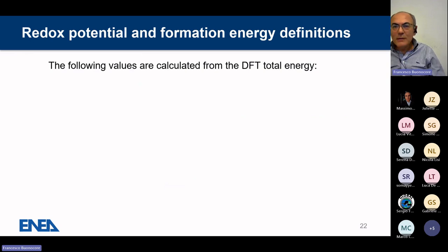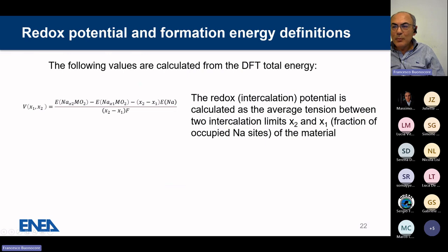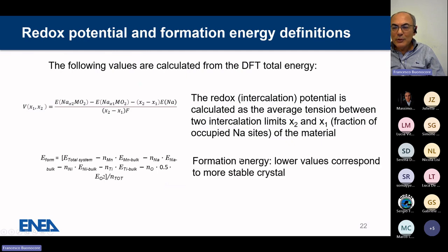So, what we do with density functional theory is to calculate the redox intercalation potentials. This is done by the total energy of different crystals, and we are interested to calculate the formation energy. The formation energy tells you how much stable your system is compared to the elements in the pure state, when they are in their more stable state. So the calculation of formation energy tells us how stable your system is. So we look for systems with very low formation energy, and the redox potential is something that we require to be higher than 3 electron volt for our applications.